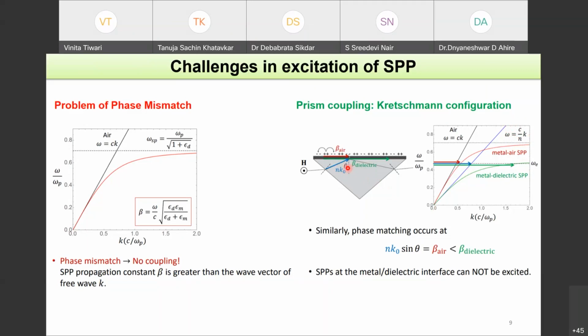After that, you can manipulate or tune the incident angle so that the horizontal component of the propagation vector, or the momentum, matches that of the surface plasmon, and this is what it is doing. You can choose your theta such that this blue line exactly gives you the same value of momentum for the SPPs also. That is where you will be able to couple surface plasmon polaritons at the metal air interface.